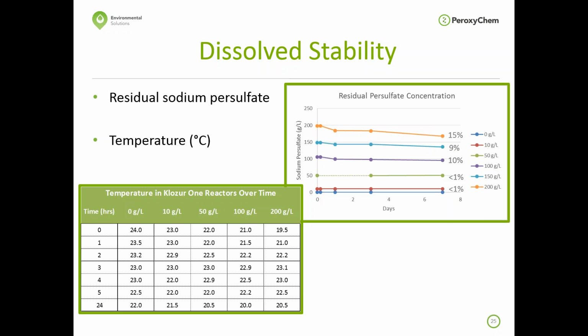But more importantly to this overall system, there was never observed, we ran this test multiple times, and we never observed any spike in temperature based on having the activator, this particular activator that is in Klozur One, in with the Klozur SP. The closest we got is really at 200 grams per liter, and the temperature came up at about 3 hours to essentially the same temperature as the control. So in terms of the long-term stability of the Klozur SP, it's really pretty stable, but you do see some degradation with increasing concentration. And then in terms of temperature, again, it's really very stable in the experiments that we've run.